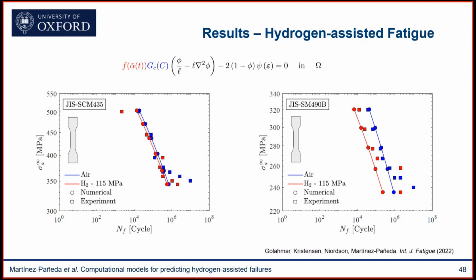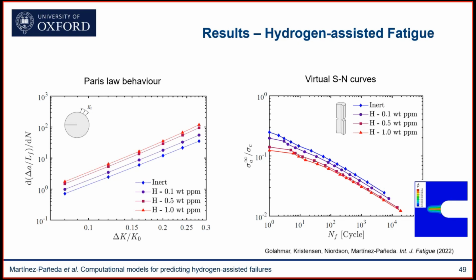But also very compelling because we are able to simulate or deliver predictions for any arbitrary choice of loading history, and also for any arbitrary choice of geometry. You can see here that we can obtain as an output of the model the Paris law behavior for different hydrogen-containing environments, and we can obtain virtual S-N curves for, again, any arbitrary loading history, any arbitrary geometry. This is a notch component, for example, and again, hydrogen contents.